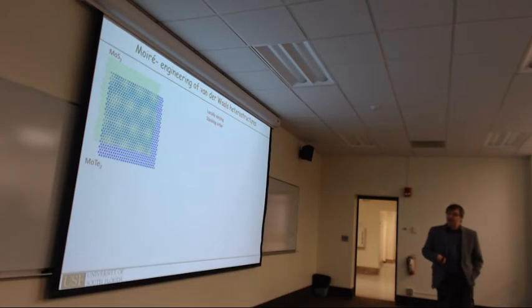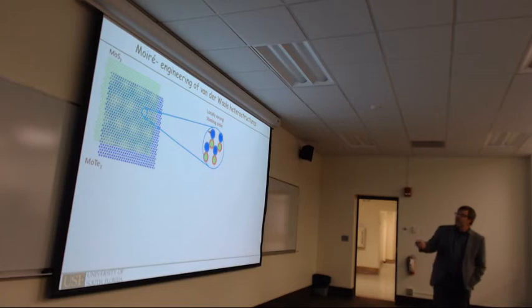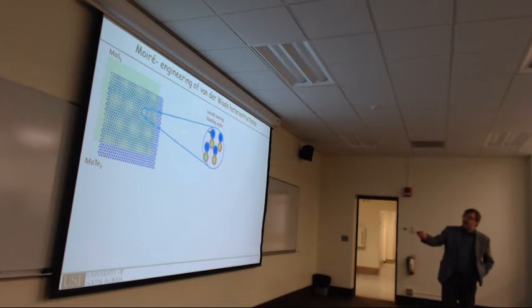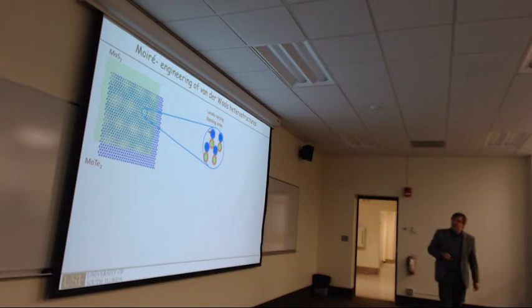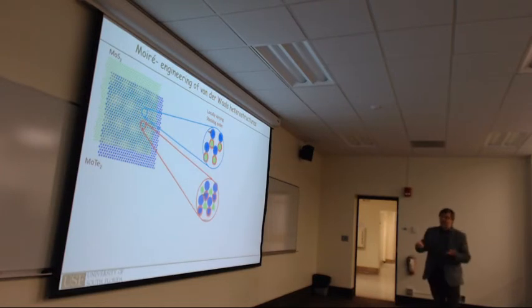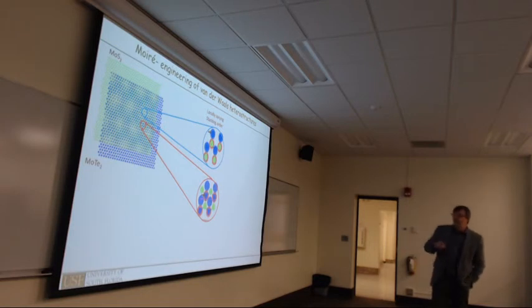If you look a little more carefully, then you get different stackings in different portions of the moire structure. So here the top layer is shown, and then the circles are the bottom layer. In some parts, you have the top layer just matching perfectly the substrate layer, but in other parts, they have more stacking as they would have in the bulk material, where one is on top of the other and the other one is a hollow site.